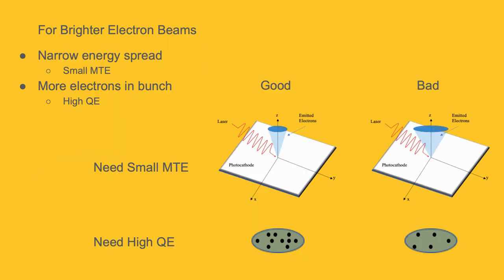The second photoemission property is called the quantum efficiency and it refers to the number of electrons that we get emitted for a given number of photons. Typically, the quantum efficiency is determined by the photocathode material and the photon energy of the laser that is used. The quantum efficiency determines the so-called lifetime of the photocathode. After prolonged use, the quantum efficiency can decrease significantly and the photocathode can no longer produce the desired electron beam.